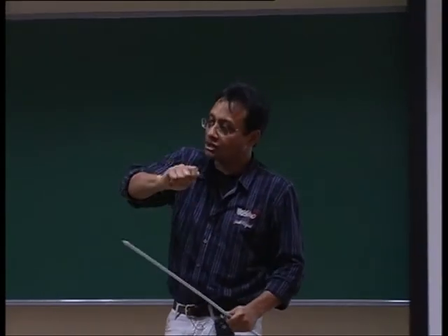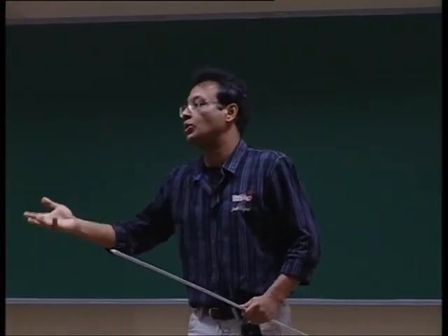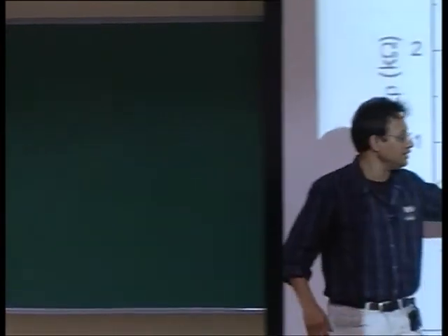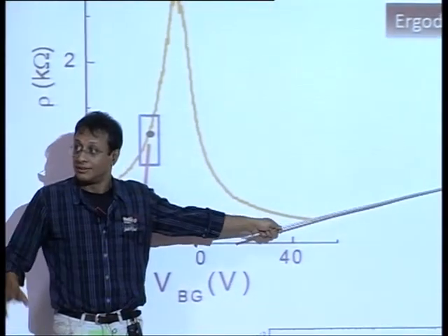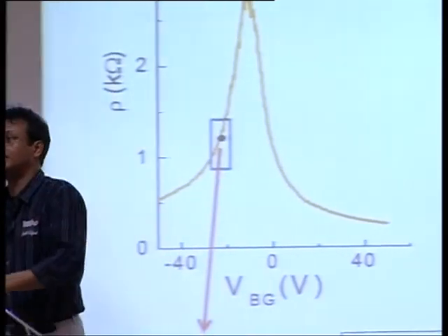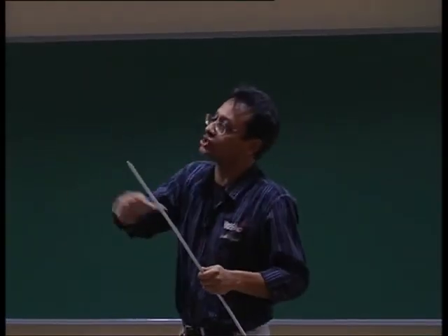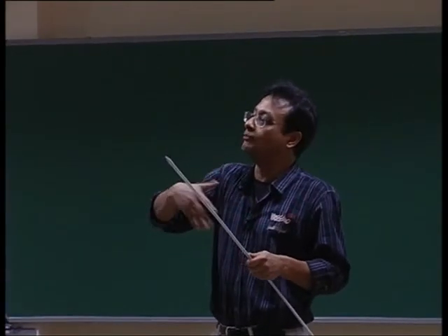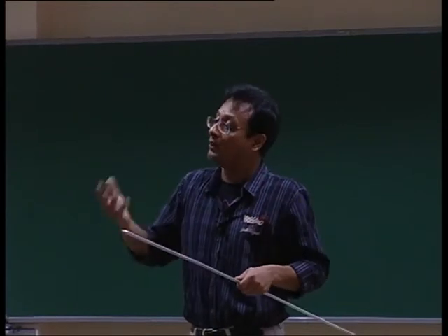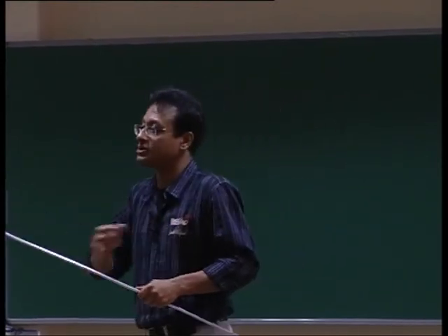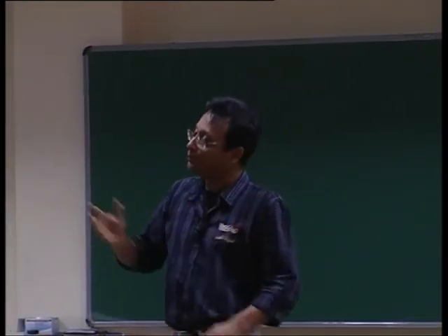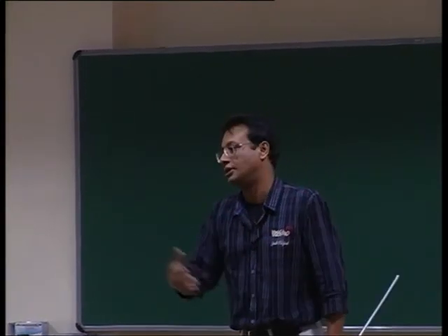Now, to quickly answer why the conductance fluctuation is decreasing: as you go down in temperature, the electrons jumping from one trap to the other get smaller and smaller in number. It is normalized by sigma squared. The reason it is decreasing with temperature is because the disorder change is becoming slower and slower. Most of the disorder is like mobile disorder, if that's the right way to say it. The number of mobile disorders is decreasing with decreasing temperature. So that's why this has a different temperature dependence than the previous one. But both of them eventually arise from the same quantum effect, the interference.